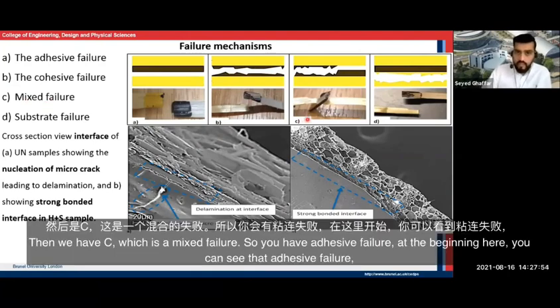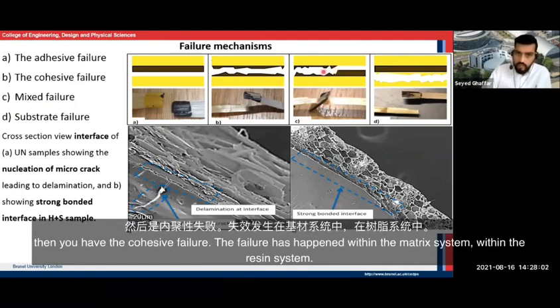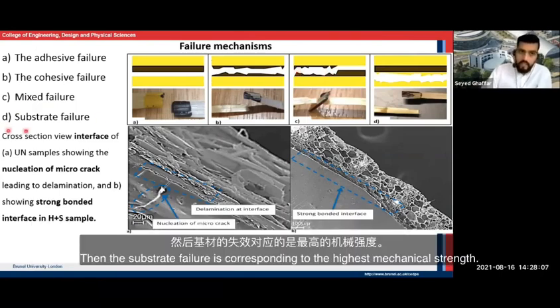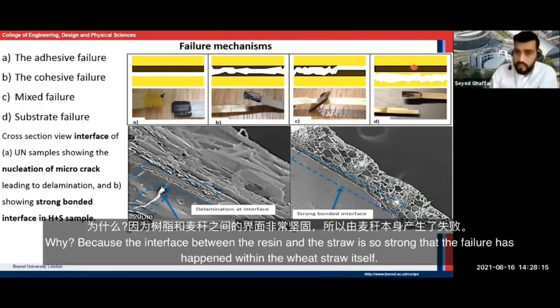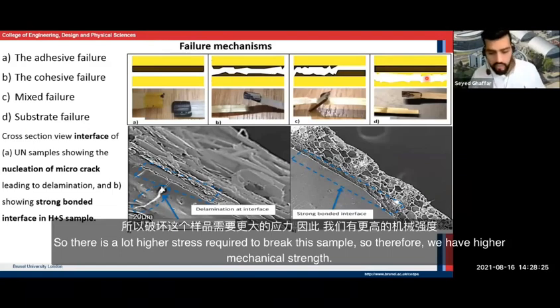Then we have C, which is a mixed failure. So you have adhesive failure at the beginning here. You can see the adhesive failure. Then you have the cohesive failure. The failure has happened within the matrix system, within the resin system. Then the substrate failure is corresponding to the highest mechanical strength. Why? Because the interface between the resin and the straw is so strong that the failure has happened within the wheat straw itself. So there is a lot higher stress required to break this sample. So therefore we have higher mechanical strength.